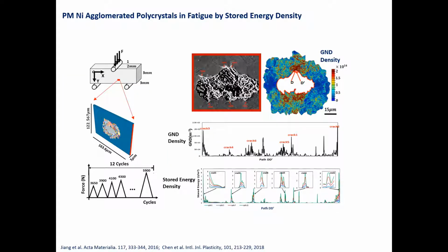Finally then on nucleation, moving to full-scale 3-dimensional polycrystals. Again, it's a nickel alloy, RR1000, a powder metallurgy alloy. Being a PM alloy, it sometimes incorporates agglomerates that come from the manufacturing process, which are brittle and act as nucleators for slip-driven fatigue crack nucleation. And you can see in the experimental observations the crystallographic slip-driven fatigue cracks which have nucleated, 6 cracks around this agglomerate over cycles.